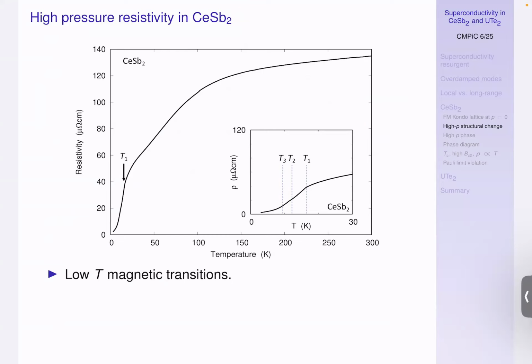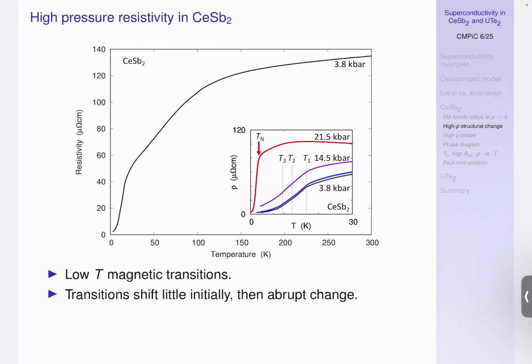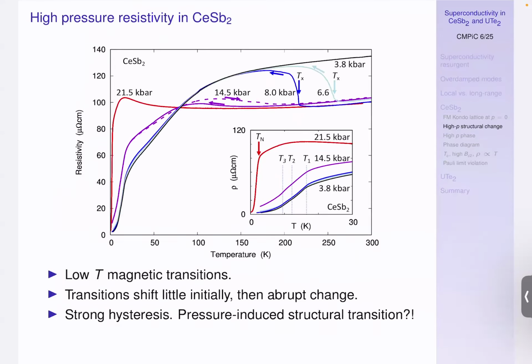So here's what you see when you measure resistivity versus temperature at different pressures. At low pressures, resistivity decreases. There's an anomaly here. When you look closely, there are actually 3 anomalies which correspond to the 3 magnetic phase transitions. And we wanted to see how they would go continuously to 0, so we have a quantum critical point. But this doesn't happen. They don't actually change much with pressure. Instead, at 21 kilobar, the resistivity curve just changes completely its appearance. And now there's a kink in the resistivity at much lower temperatures, about 3 Kelvin.